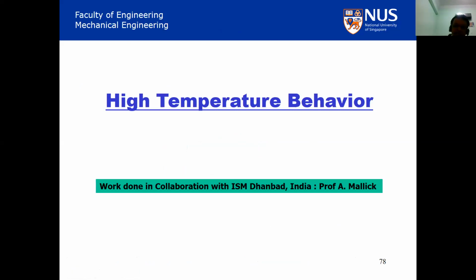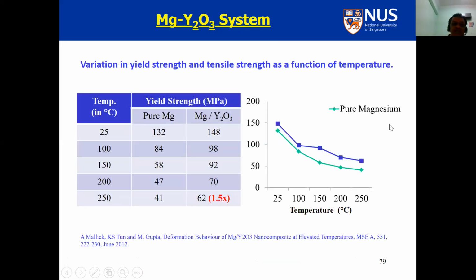High temperature behavior, part of the work done in collaboration with ISM Dhanbad. Professor Ashish Malik is sitting there. And what you see here, at all the temperatures on the x-axis of the graph, is that the composite with the blue squares always remains superior to the monolithic material.